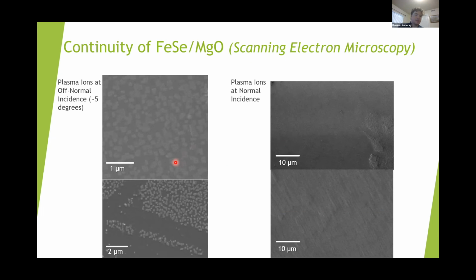So through scanning electron microscopy, we can see that at the off normal incidence at about 5 degrees off, you can see that these lighter squares are the iron selenide islands growing. And this is a larger scale just to see these gaps that come between these islands. And so we can see that with the same growth methods for the off normal and normal incidence, we have a much more continuous layer where we can't really distinguish major or minor islands around. There are more major groupings together. And from this, we can conclude that there is a more continuous layer in the normal incidence. And that would lead to a further study down the line of the point at which these islands turn into a continuous layer.